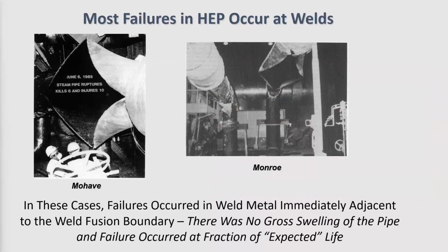Now, where the problem has come in is that most of the failures that occur in these piping systems occur at welds. And of course, in the high energy piping, that means that the damage that occurs, the welds open, does involve creep, which means in turn that we have to consider the complex structure of the weldments in trying to determine what will dictate the life of the component.